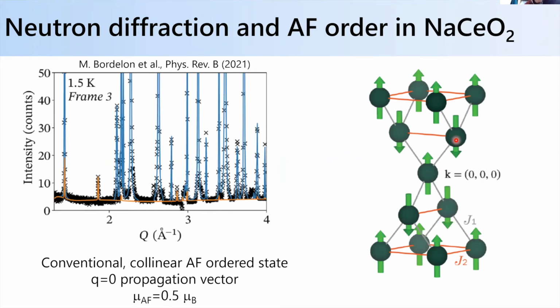And the ordered moment's about a half a Bohr magneton, which was done with a PowGen diffractometer, which is a time of flight source, which has much better statistics for neutron diffraction than the neutron diffraction data we have on the sodium cerium O2. So it suggests that we were just sort of missing the ordered moment in the sodium cerium O2 system.